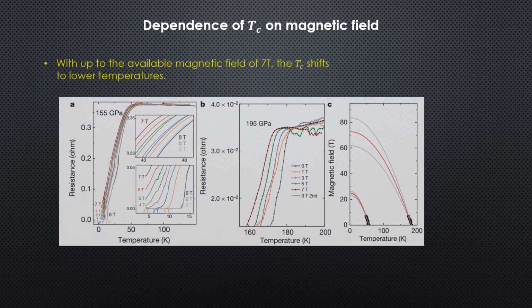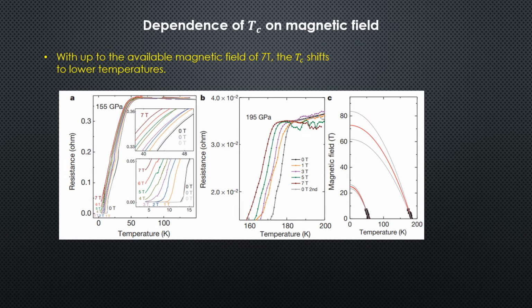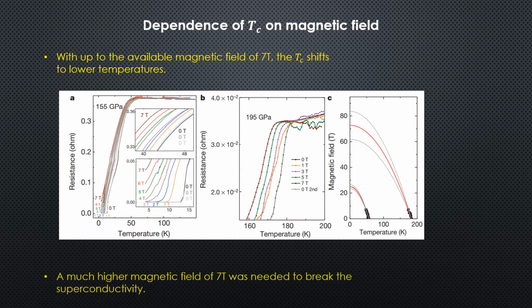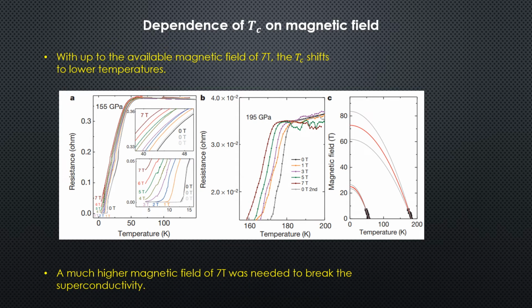Tc is also strongly dependent on the magnetic field. As we increase the magnetic field from 0 Tesla to 7 Tesla, the critical temperature Tc shifted to lower temperatures. A much higher magnetic field of about 70 Tesla was needed to break the superconductivity.